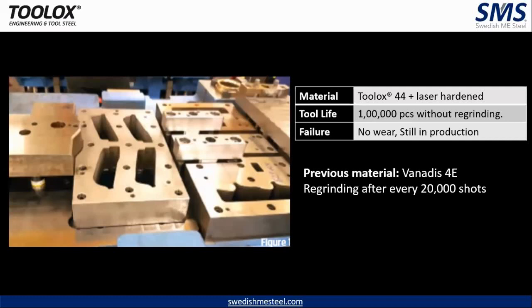Previously, they used to regrind after every 20,000 shots. Even though they were getting the total tool life, they had to do the subsequent regrinding after every 20,000 shots. With Toolox 44 plus laser hardening, so far we have done 100,000 shots without any regrinding. That's the benefit the metal can give you.